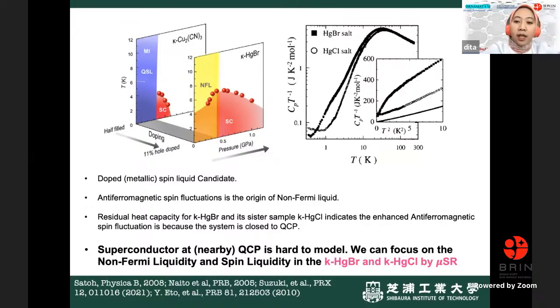Okay. Both mercury brome and mercury chlor indicate antiferromagnetic spin fluctuations because the system is close to the so-called quantum critical point, the QCP, because at low temperature there is competition between the superconducting state and quantum spin liquid state. And this situation is determined only by temperature. The superconducting state nearby that kind of quantum criticality is hard to model by theory. So that's why I need to study by experiment. Then we can focus on the non-Fermi liquidity, the charge situation, and the spin liquidity in the spin situation in mercury brome and mercury chlor by mu-SR.